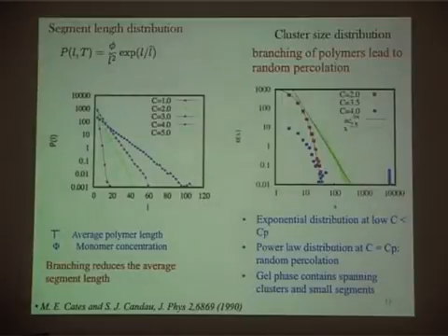Yeah. So when you see branching, is it a physical branching in which you have the local micellar curvature going from positive to negative? So we don't have that here, right? We just have these beads. So basically there is an attraction between these beads. If you don't have this three-body interaction, then you will actually get a spherical cluster of all of them coming together. So it's the three-body interaction which controls the branching here, because they want to be straight. The only parameter here which controls the branching is the three-body interaction. And in a real system, it will be salt concentration and things like that.